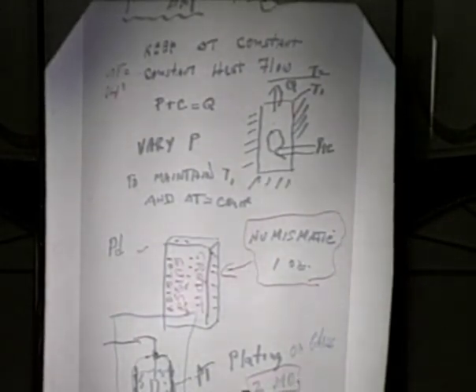We terminated the experiment because we weren't quite sure about the calibration, and basically, although we had intended that we would get recombination on the platinum here, the platinum plating was insufficient and we were losing electrolyte.